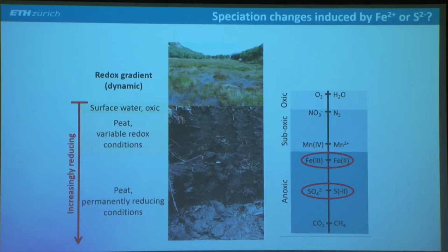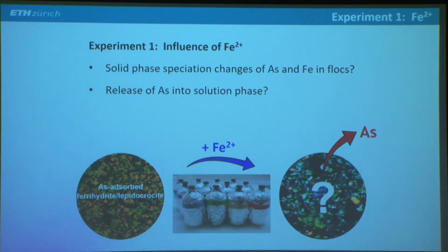So now we know what is in these flocks, and now we did an experiment to look at what happens if these flocks are exposed first to iron 2 and then to sulfide. So the experiment is fairly simple. We take a flock suspension, put it in these septum bottles, spike it with iron 2, and then follow the speciation changes over time, and also follow the arsenic release.